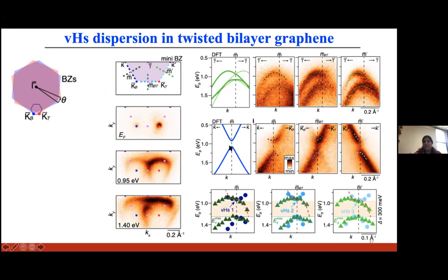And next, what we can do is take the ARPES cuts around these M points in the orthogonal direction. And when we do so, it reveals that we have these Van Hove singularities and a mini gap. And the mini gap here is about 300 meV. And the horizontal line here marks the maximum energy below the mini gap.